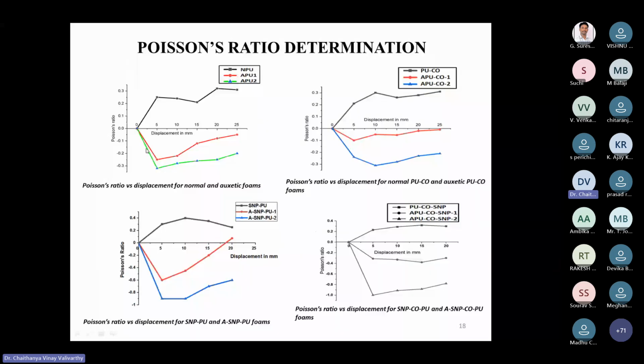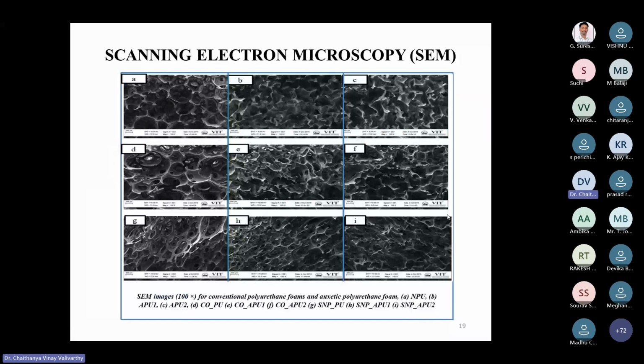If you stretch the foam for 5 mm displacement, 10 mm displacement, 15 mm, initially it behaves like an auxetic, and then it goes to behaving like a normal material. So auxeticity is completely non-linear. This behavior is completely non-linear inside foams. These are the PU foams with castor oil, these are the PU foams with silver nanoparticles, and these are the PU foams with CO and SNP. These are the scanning electron microscopy images. Here we can see the buckling phenomenon.